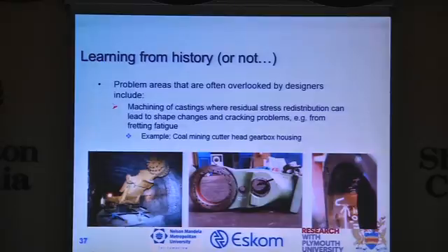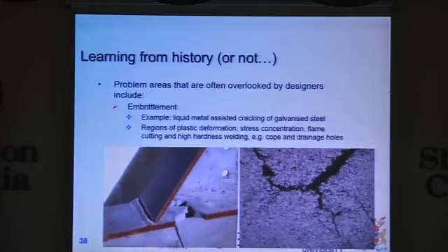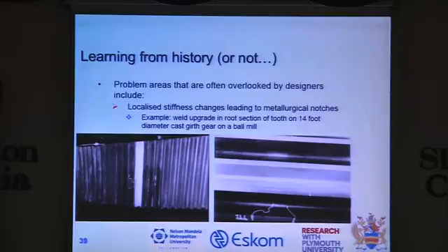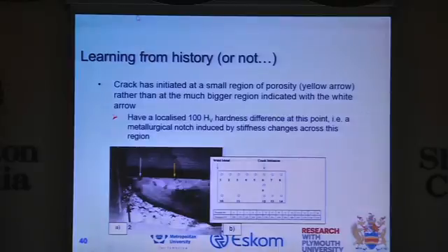Some case studies that Prof. James put in here, I'm going to skip them because of time, but the one that I think is important is the specific one where when you machine a casting, you get distortion, and that distortion results in fretting fatigue. It's a residual stress issue. This embrittlement here with flame cutting, incorrect welding processes, it's a residual stress phenomenon. This is a 14-foot diameter cast girth gear that was weld repaired. The fatigue crack grew slightly away from the weld repair, because not the weld repair, but your support ligament is affected by the residual stresses. You can read the details on that in the paper.